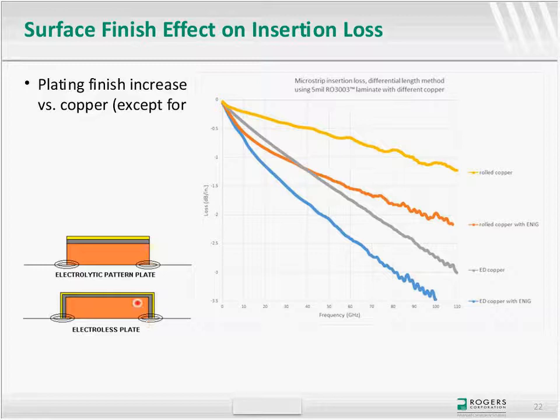But this is traditional. And the current that travels on the circuit really travels mainly on the edges, so you have a lot of the current traveling on that plating. So when you see here the difference of some of these finishes, we can see what happens when you take rolled copper with electroless nickel immersion gold, which is the most common finish in the market for plating, for protection of the copper from oxidation. You have traditional ED copper here, and then once you put the plating on, you see the impact.